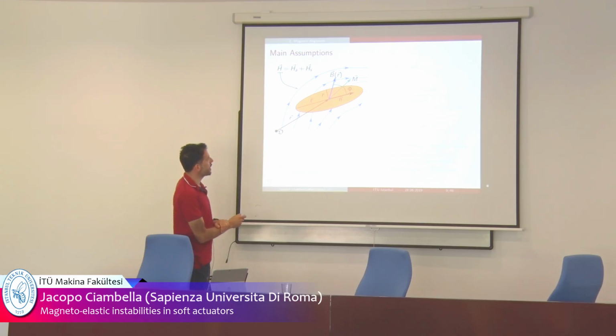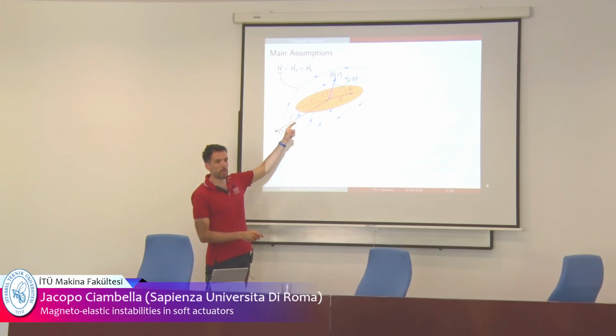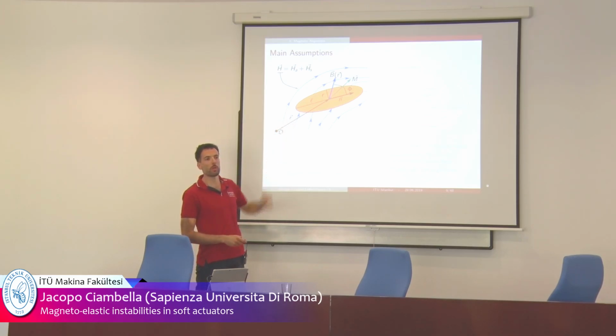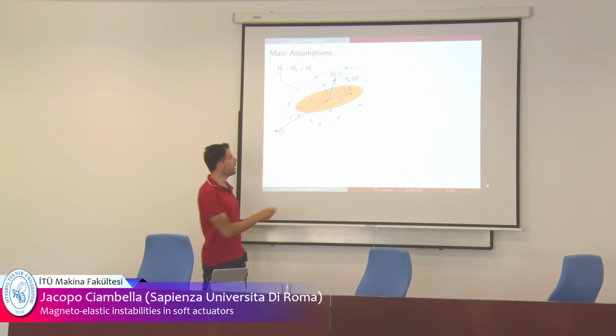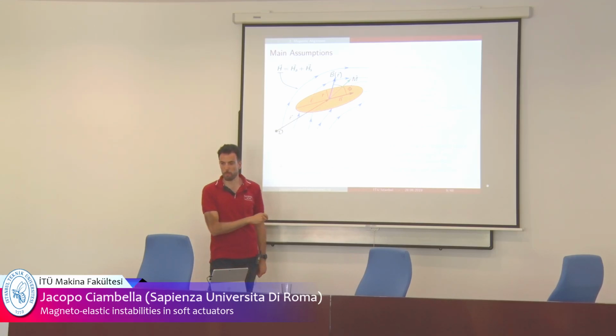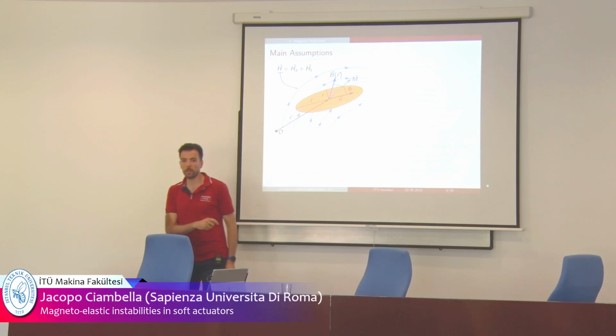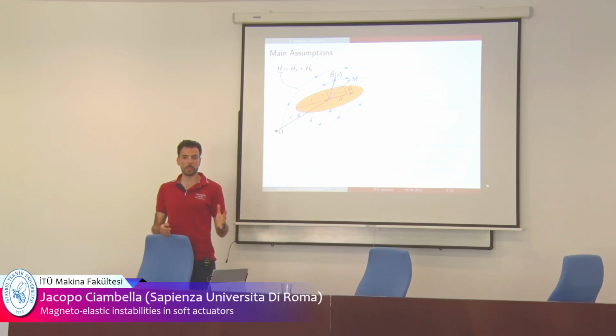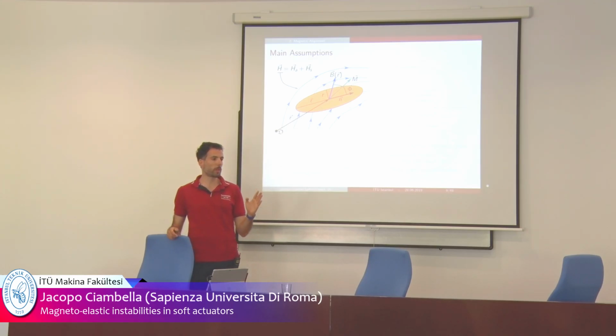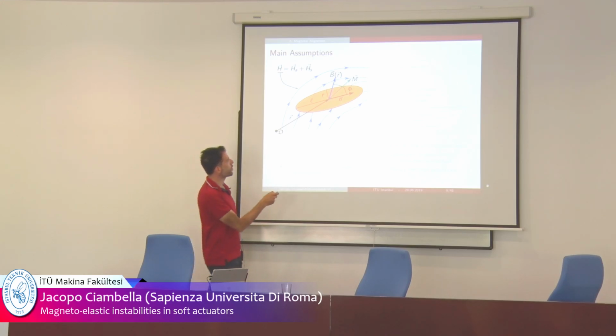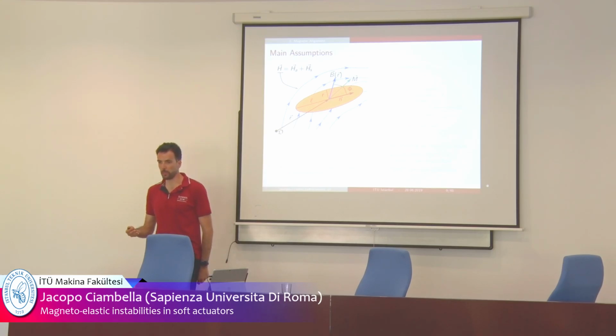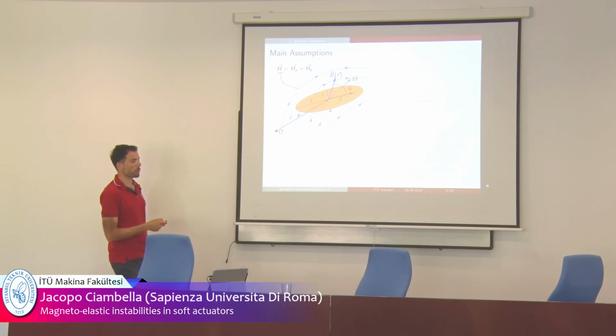And with small n here, I will indicate the main axis of the ellipsoid, which will give you the orientation of the particle at time t. And as you can see here, there will always be a mismatch between the orientation of B and the orientation of M. What will happen from the physical point of view is very simple. It's the principle of the compass. M wants to rotate to be parallel to B, right? And this is the main mechanism. So these particles want to rotate in a way that M and B are parallel.